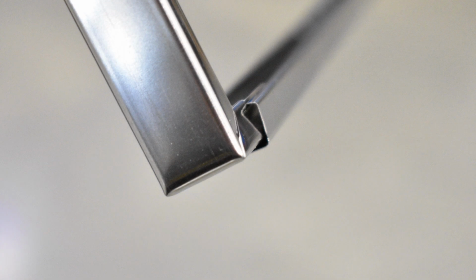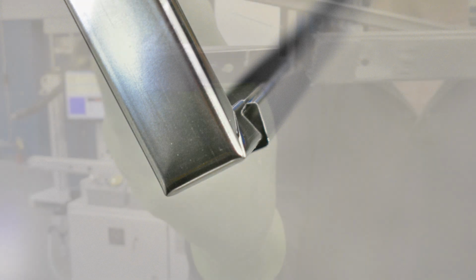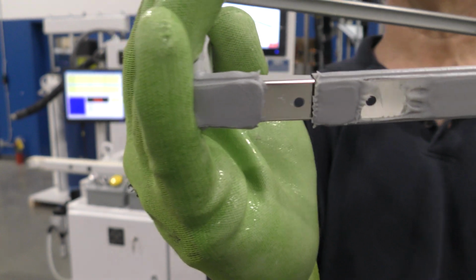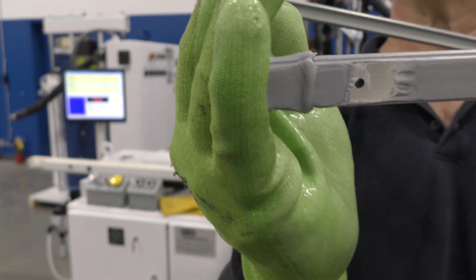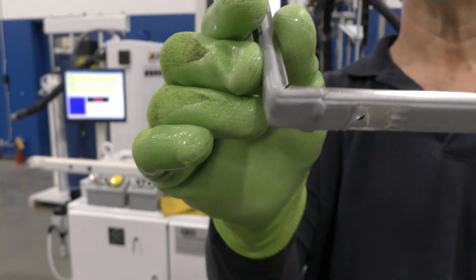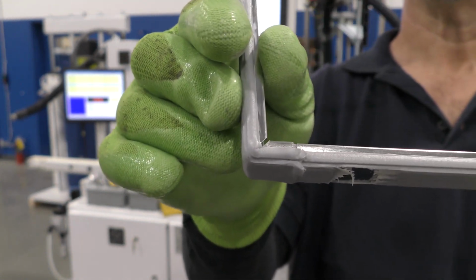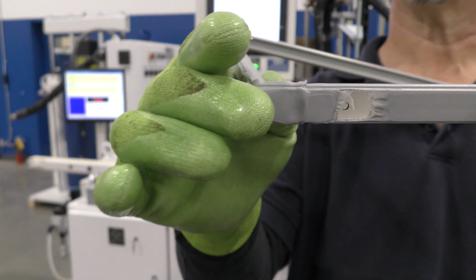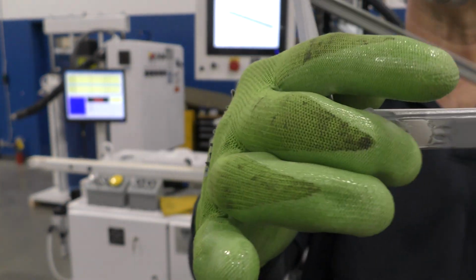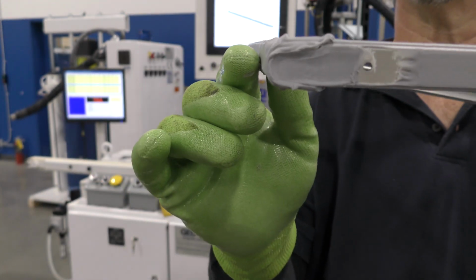The sides of the tab should be under the side lips. If the tab is inserted at an angle, tab sides may not insert under the lip, creating a large gap on the back of the spacer and excessive corner flare. Once the tab is fully inserted, the operator should gently press the back material to mend the ends together and press the material into the seam while it is still hot. Do not press too hard or wipe the material, as this may leave the metal exposed.